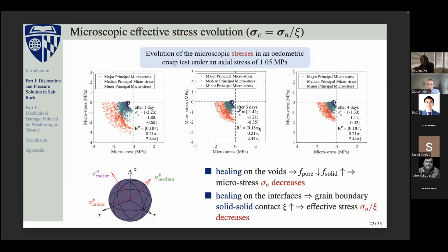First of all, we present here the microscopic effective stress evolution. You can see that from left to right, as time evolves, this effective stress decreases. The magnitude of it shrinks a little bit. Here are two explanations of that. The first one is healing of the void. Because the volume fraction of the solid increases, the micro effective stress will decrease. And the second explanation is that we also have healing on the interface. The healing on the interface causes the grain boundary solid-to-solid contact to increase. Therefore, the effective stress decreases.